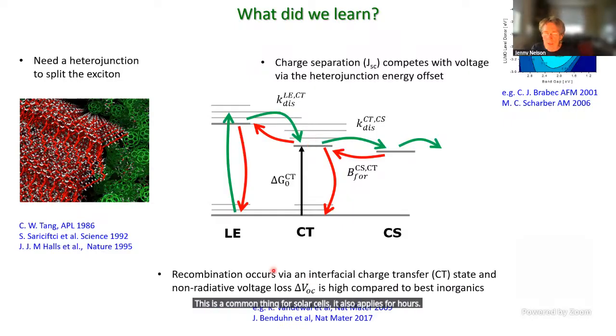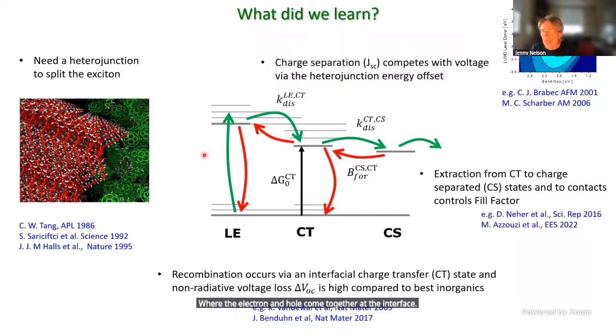Then the dominant loss pathway is recombination, and that occurs most efficiently through these interfacial states where the electron and hole come together at the interface. And then finally, when we want to extract this charge pair from the interfacial state into an external circuit, the efficiency of that process will control the overall operational power conversion efficiency and the fill factor. So I'm going to leave it there.